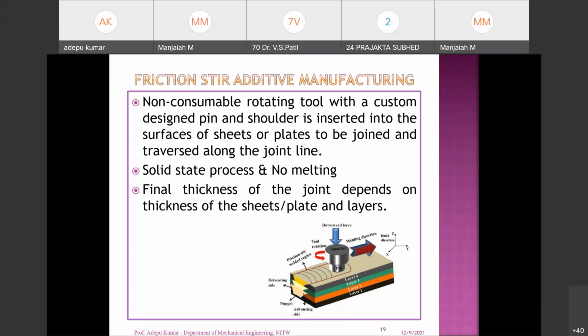If the material flow is improper, then you do not accommodate sufficient material at the backside of the pin. That leads to the creation of a slot. When you talk about a slotting operation, you are removing material from the stock, and after removing it becomes a slot. Instead of removing the material, we are trying to accommodate the same material at the backside of the pin. Even this happens in friction stir additive manufacturing if you are not providing sufficient heat generation.